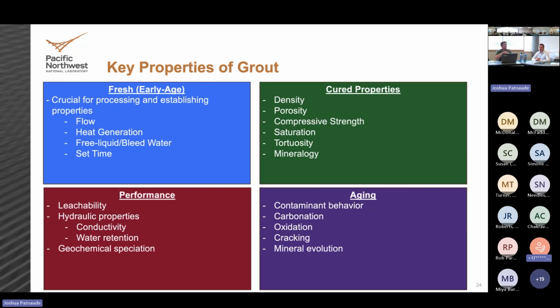But if we're doing waste management, one of the main guidelines laid out in the NRC technical guidelines for waste forms is that you want to have less than 1% free liquids on your material. Because if you're immobilizing a liquid waste, that bleed water sitting on top is your liquid waste, essentially. So you want to design mixes that don't produce a lot of free liquids. That's fairly straightforward to do, and nearly all of the ones that we've evaluated in the last decade and a half for waste immobilization here at the site show reabsorption of any free liquids within a day.